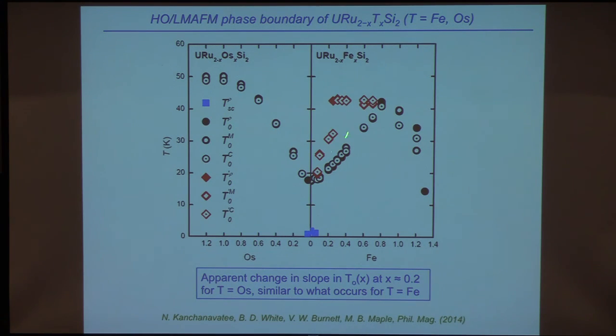So this is the iron phase diagram that I showed you. Again, ignore these points right here. This is on polycrystalline data. So this is increasing the iron concentration, reducing the unit cell volume. This is substituting osmium, increasing the unit cell volume, and you see that the same thing happens, and the phase transitions even go to higher temperatures when you do that.